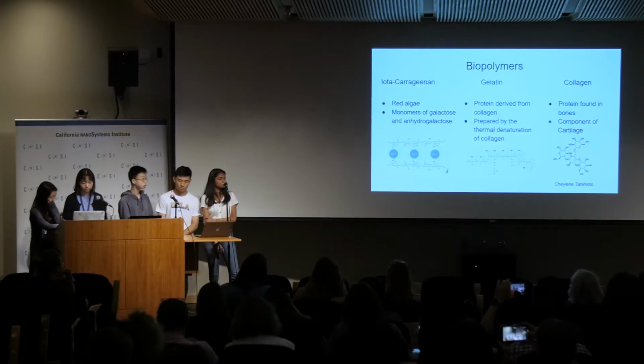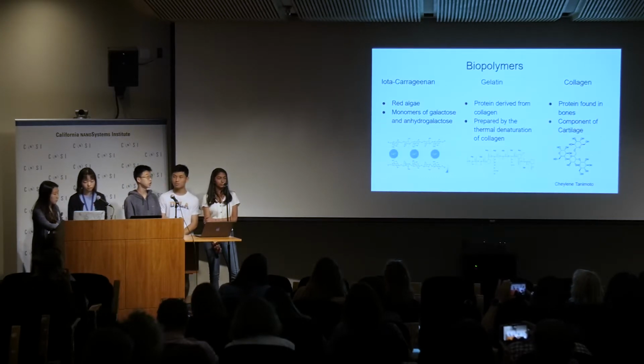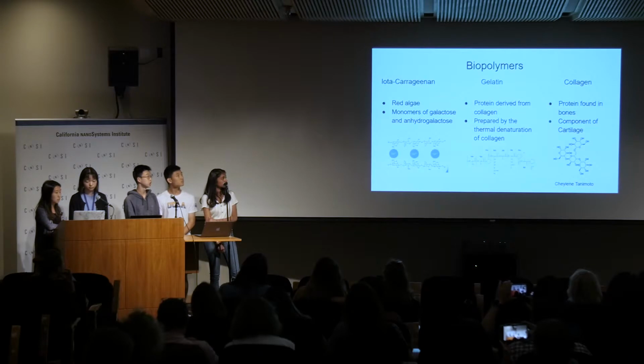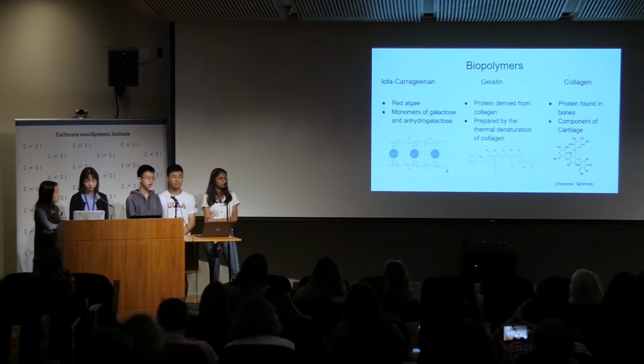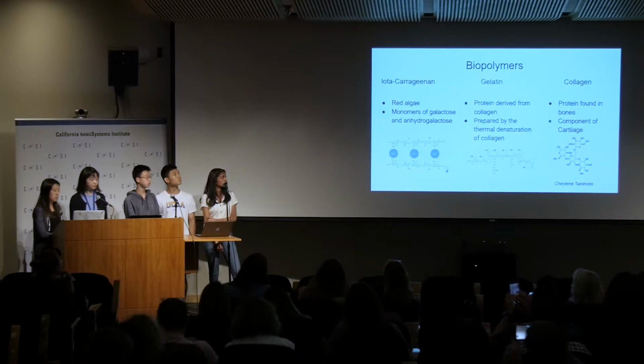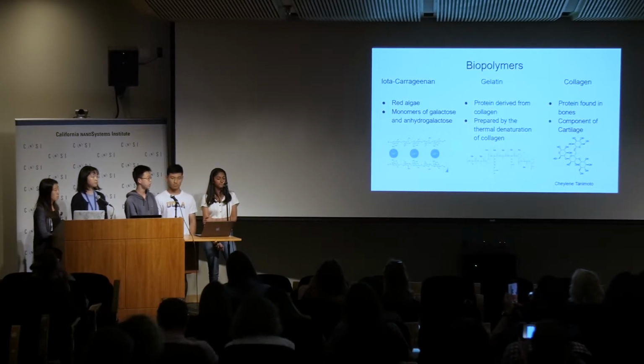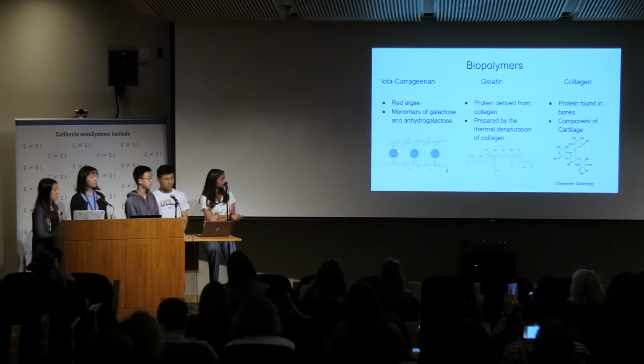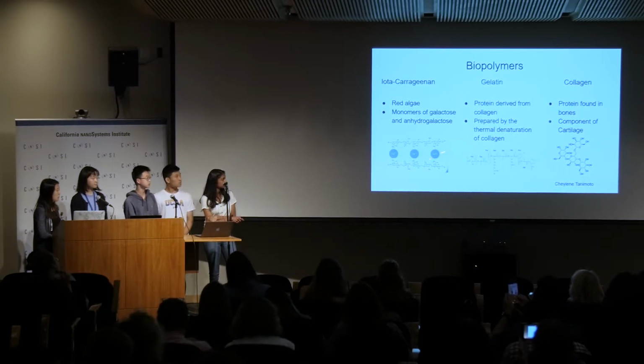The biopolymers we used in this lab are iota-carrageenan, gelatin, and collagen. Iota-Carrageenan is a polysaccharide polymer that comes from red algae. It has monomers of galactose and anhydrogalactose. It forms a structure by forming bonds of calcium ions, and the calcium ions bond with the sulfate groups.